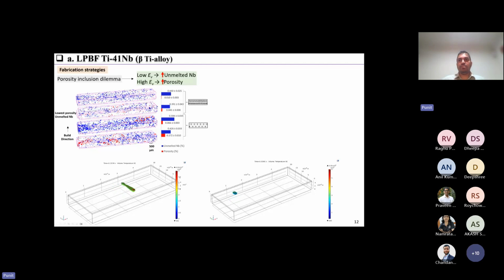So this is where the PhD student I was working with came up with a brilliant idea. In normal processing techniques, where you see the melt pool, the laser beam speed is really slow and you have a stable melt pool. He came up with the idea that we can input much more energy into the material and still have a stable melt pool if we significantly increase the laser scanning velocity. And when we did that, we were able to significantly reduce both porosity and unmelted niobium particles, as you can see in this example, because we now had this high volumetric energy density during processing of this alloy.